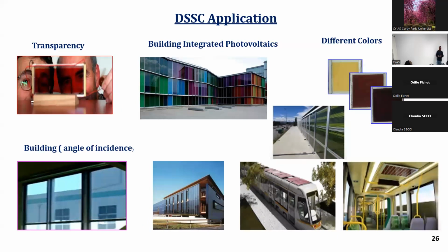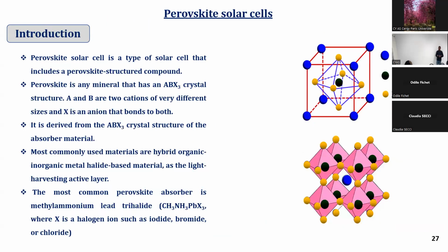Another emerging photovoltaic technology is the perovskite solar cell. It was introduced and started in 2009, but till now it has reached 26.1% efficiency. This solar cell is mainly based on the perovskite structure, the ABX3 crystal structure, as the absorbing material. It mimics DSSC. In DSSC, the light absorber is an organic dye, but in the perovskite solar cell, perovskite is the light absorber. Another difference: DSSC uses an iodine electrolyte, while perovskite uses a hole transport material. Mainly the perovskite used is methylammonium lead triiodide.